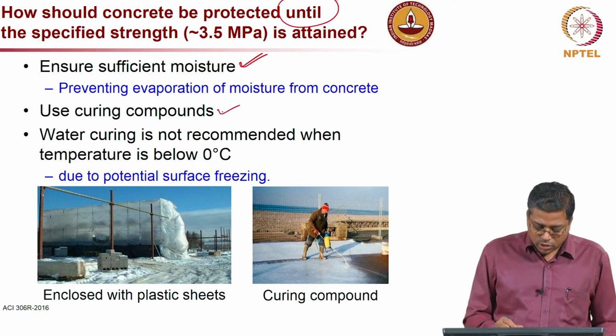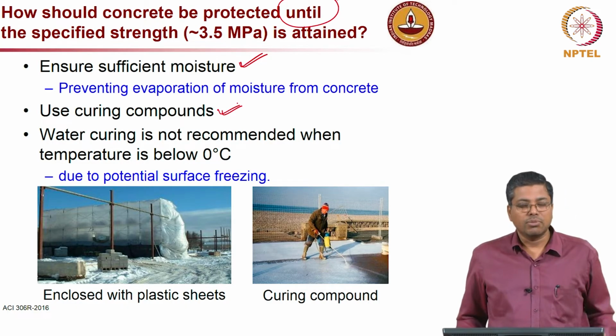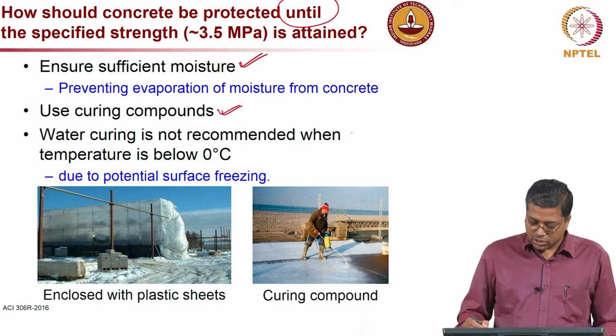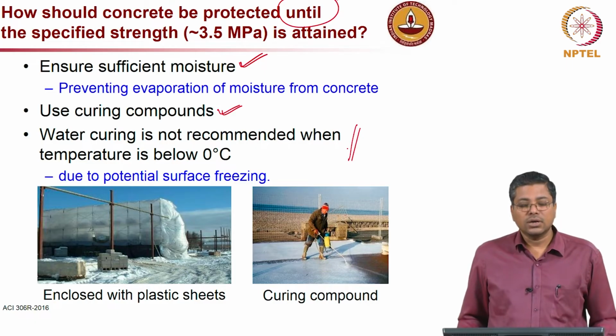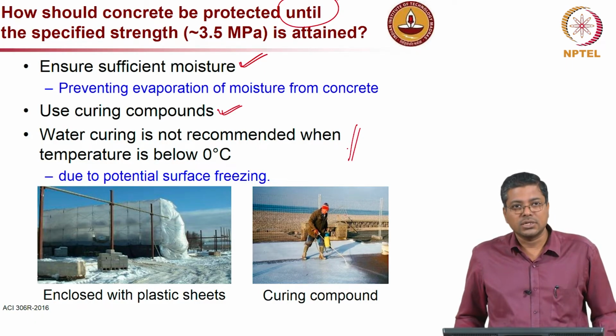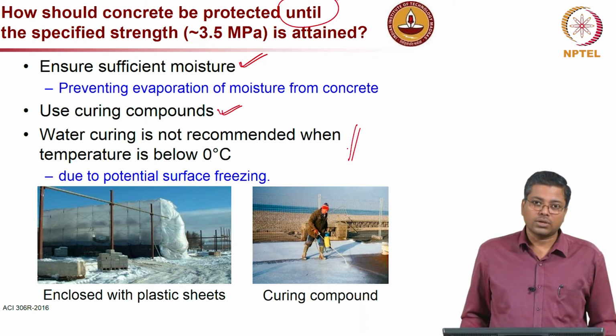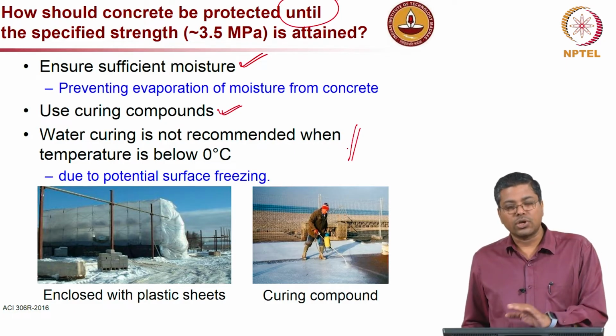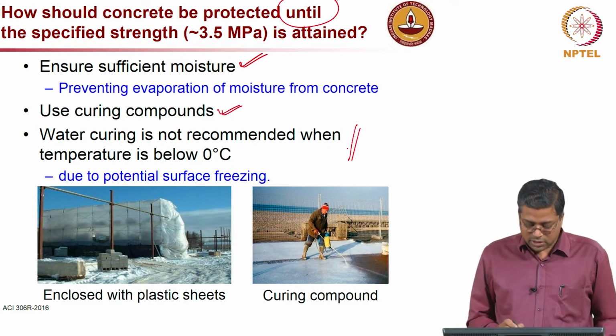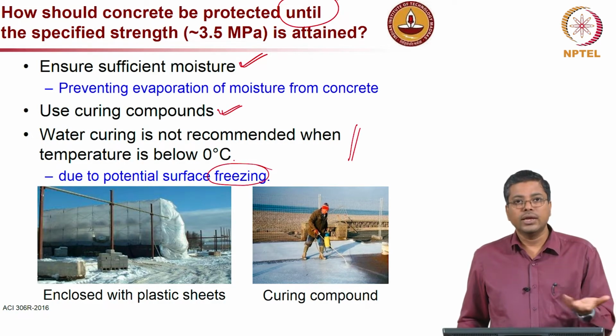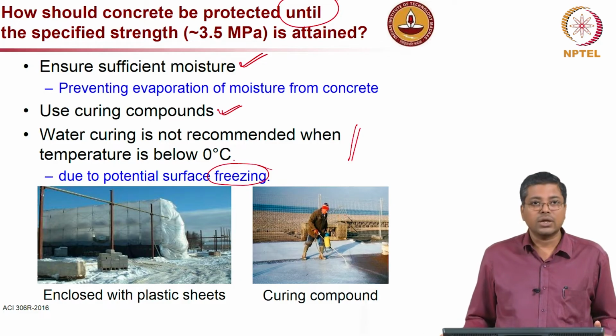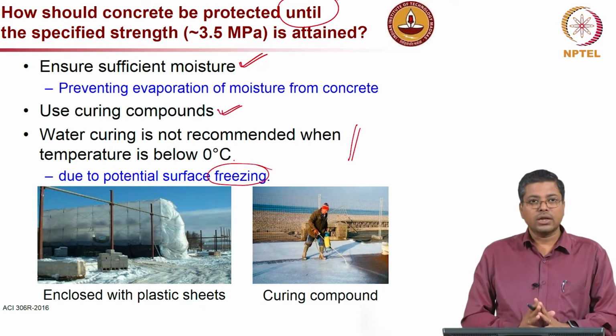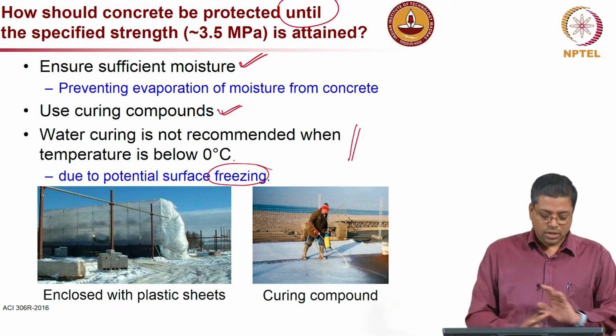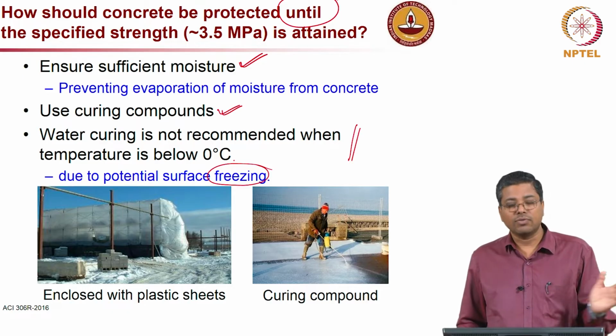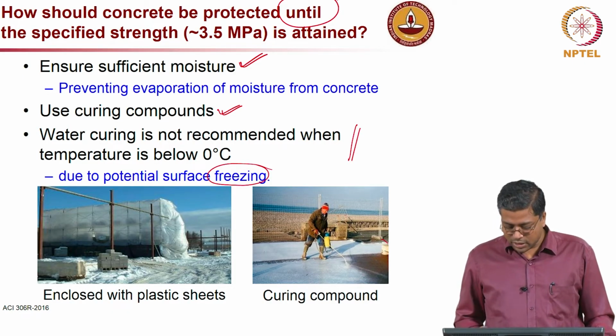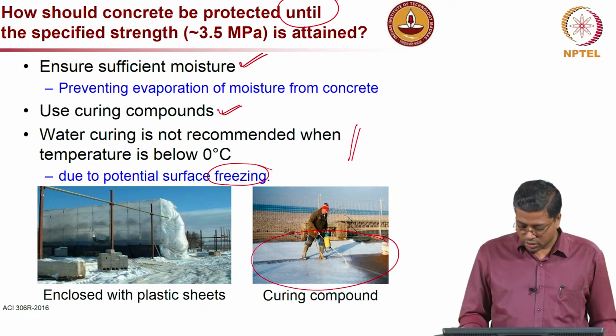And then also we can use curing compounds to prevent the moisture loss from the surface. And one important thing to note here is when the temperature is in the freezing range, like less than 0 degrees Celsius, it is not recommended to use water curing, because that water which you use for curing will stay on the surface of the concrete, which eventually can freeze and which will lead to further damage to the concrete. So, water curing is not a recommended idea. So, main thing to do here is first protect your concrete structure with a plastic sheet or something like that, so that evaporation does not happen, and then another way is providing a membrane, which is basically the